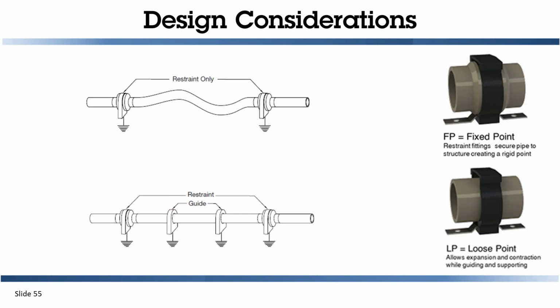So if you only had two restraint points, two fixed points on either end of the pipe, with the expansion the center portion of that pipe will become like spaghetti, and you're going to have a visually unpleasing pipeline. To make it straight, we actually want to guide that expansion so it does not sag. So we use loose points in between those fixed points so that the pipe will remain straight.